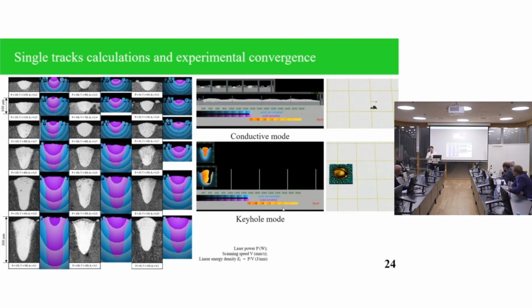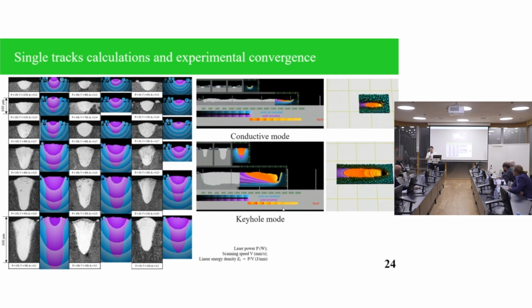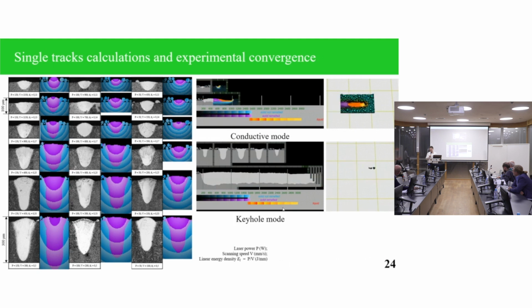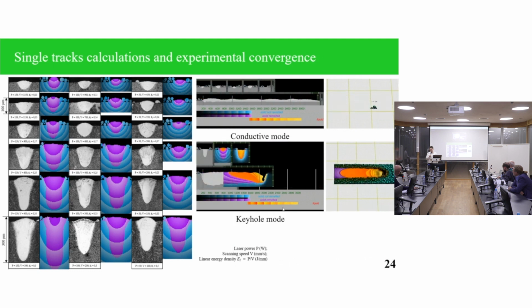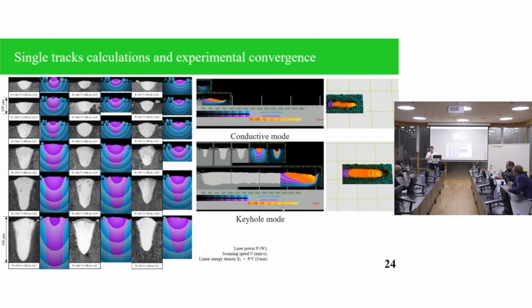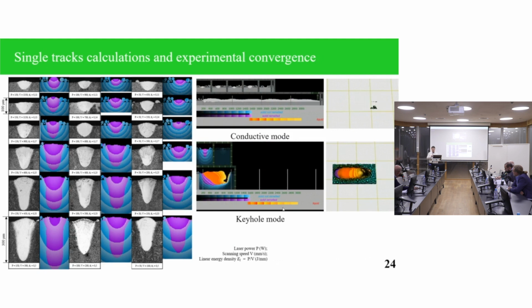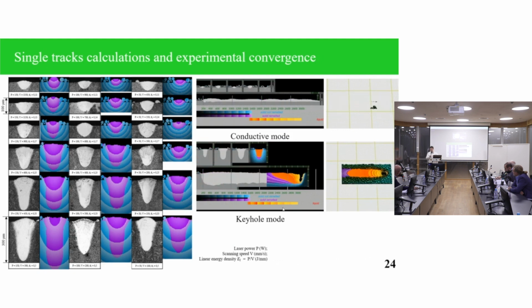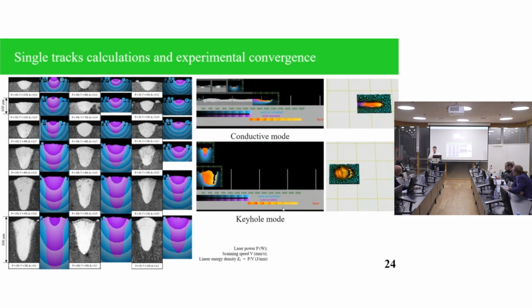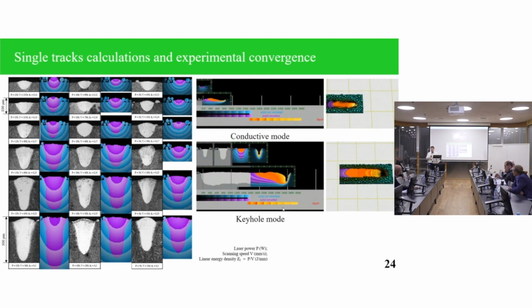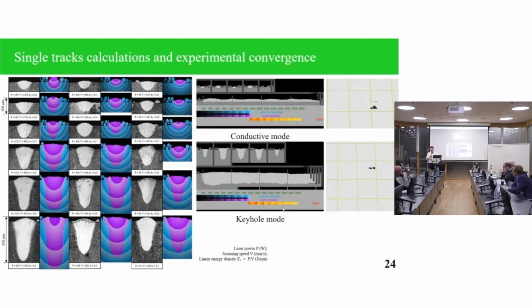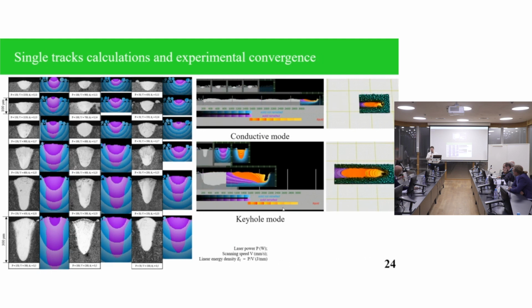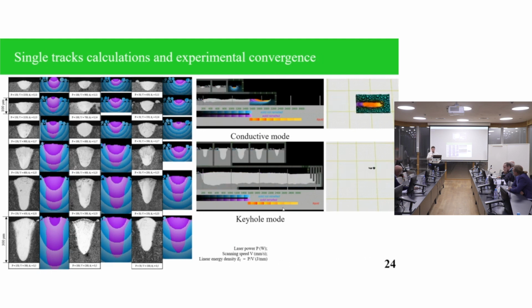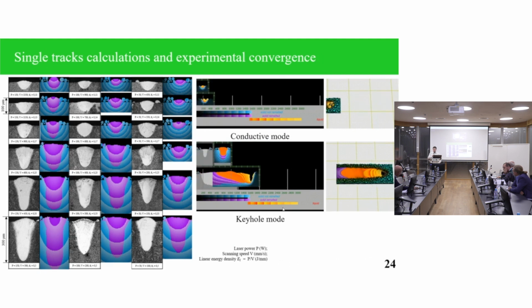Sorry, the calibration procedure is completely different. In this software, we do not calibrate anything. We have only thermophysical properties known from literature or experiment. We use them in the equations, and then we calculate the temperature fields and the velocity field inside the melt pool, and finally we obtain the cross-sectional view. So you don't perform closed loop optimization, you prefer to believe the literature data, and even if the literature data leads to a result that doesn't agree with your experiment, you still insist on believing it. Is that what you're saying? No. You don't feel tempted to adjust it to get a better agreement?